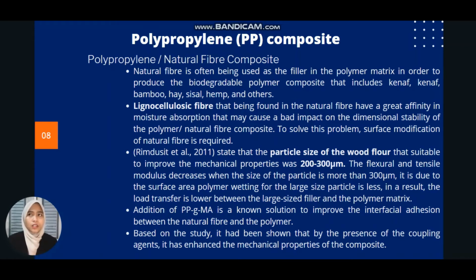So based on the literature review that had been made, some of the research had used sodium hydroxide to make surface modification on the natural fiber. So according to Rimdusit, he stated that the particle size of the wood flour that's suitable to improve the mechanical properties was between 200 to 300 micrometer. But if we use more than 300 micrometer, the flexural and the tensile modulus will decrease because the surface area of polymer wetting for the large size particle is less. As a result, the load transfer between the large size filler and the polymer matrix is poor.